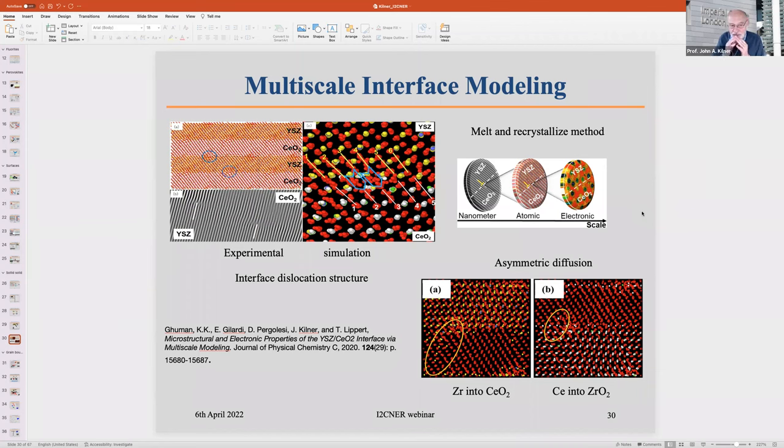Well, first of all, let's talk about the surface exchange coefficient. There have been numerous studies. You've done some work, I've done some work at I²CNER that show that when you introduce water vapor or in fact carbon dioxide into the exchanging gas atmosphere, then you accelerate the effective K that you see. And the fact is that the water molecule exchanges much faster than the dioxygen molecule. The dioxygen molecule is very tightly bound, and breaking that bond is quite difficult. But water is easier to dissociate.